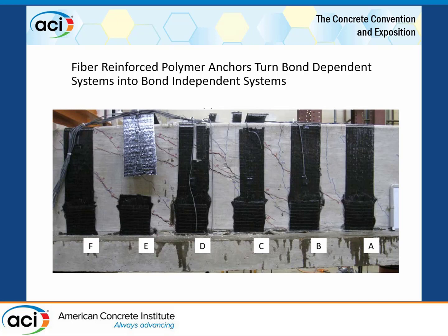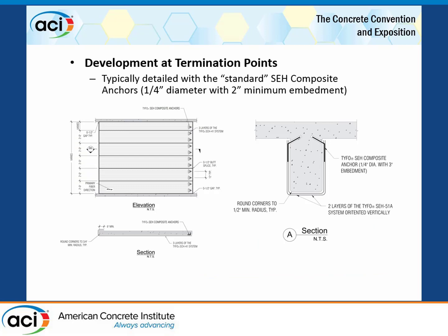This was completely debonded on purpose. The only thing we had is a three-sided and then fully anchored, and we actually performed much better than I expected. I would still, by the way, suggest that you can treat it as a bond-critical application and still bond it, but we wanted, this is fun to do in a lab, completely debond it. I wouldn't necessarily suggest that at this point in time in the real world. But we did prove, in fact, that you can take debonding out as your governing strain, as long as you detail it correctly. And that's a longer conversation.